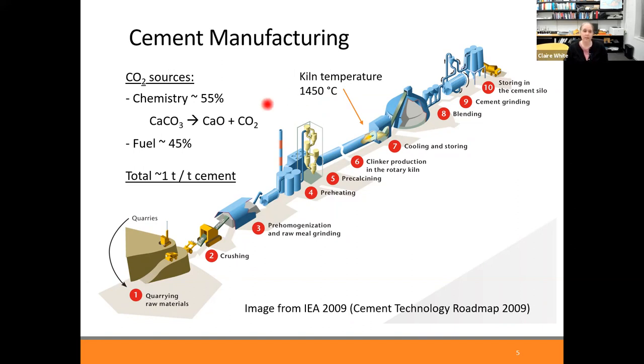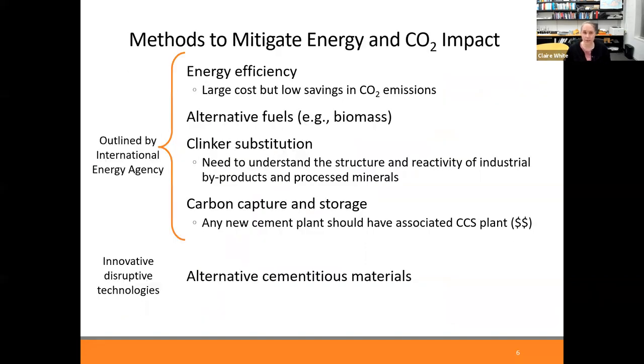And so if you look at the fuels that are used to get to these really high temperatures, such as petroleum coke, the burning of those contributes about 45% of the CO2 emissions. And then the decomposition of the limestone contributes about 55% of the emissions, such that if you look at 1 ton of the cement powder that's produced out of the plant, you're getting about a ton of CO2. So this is not insignificant in terms of the CO2 that's been generated. Now, the industry and the wider community are very much aware of these CO2 emissions. And so there's been a lot done in terms of outlining the various approaches to reducing the CO2 emissions associated with this industry.